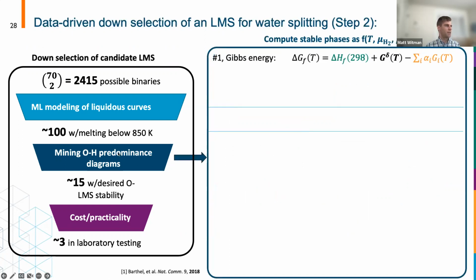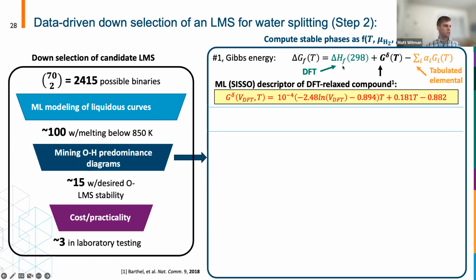So the more important part then is how can we determine which ones have the right thermodynamics for this proposed water splitting reaction. So after we narrowed it down to about 100 materials with the desired melting range, we wanted to create what are called these OH predominance diagrams. In order to do that, you need to know the Gibbs free energy of the different phases in the system. And there was this interesting recent paper where Bartel et al. used this SISSO model to derive a descriptor that you can use to correct DFT calculations to get the Gibbs free energy of that phase at a given temperature.